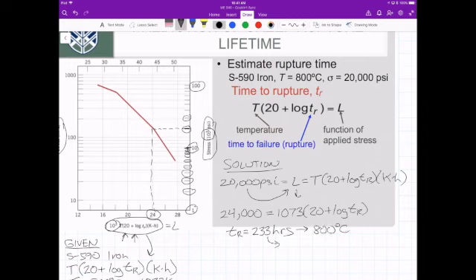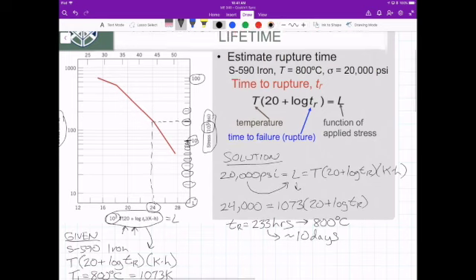And how long is 233 hours? 240 hours would be 10 days, so it's approximately 10 days. So at an elevated temperature, if you stress iron 20,000 psi, it'll rupture in 10 days. Okay, so that could be a problem.